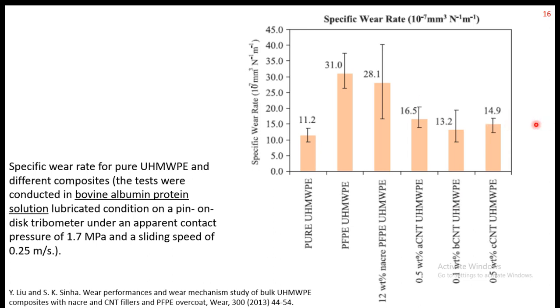When we conducted the sliding test with bovine albumin protein solution as the lubricant, we found that all of the composites we made of UHMWPE gave wear rate which was slightly higher. Even the CNT, which you saw in the previous paper, gives wear rate lower than pure UHMWPE. However, in our case we did not find that. We found that the wear rate is either nearly the same or slightly more. This was a bit disappointing because the normal expectation is that when we add strong fillers to a polymer, the wear rate goes down.